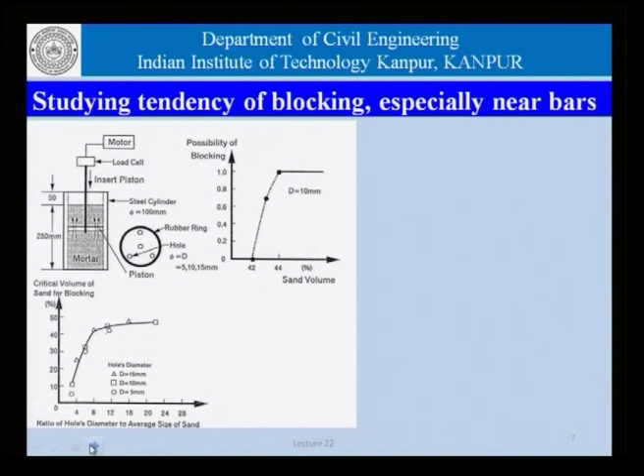Building on that argument, we had discussed this slide, which talks about the possibility of blocking and the critical volume of sand required for blocking if we were doing an experiment as shown here, where in a small cylinder we are trying to push a piston which has a configuration like this, having holes of different diameters, and these diameters are related to the particle size that we have. And we had talked about a sudden change that is occurring here and a relatively sudden change which is occurring at around this value here.